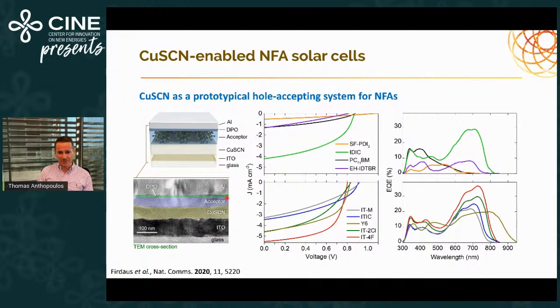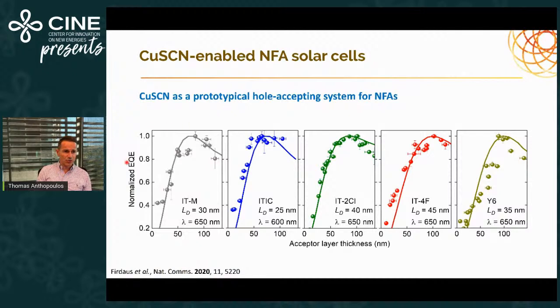Many different acceptors have been tested, and a handful of those are shown here. I think we tested over 10 acceptor materials at the time. And then what we've done, we were measuring the external quantum efficiency of the device as a function of the layer thickness of that NFA, the non-fullerene acceptor. And we could actually resolve that peak performance somewhere at the critical thickness.